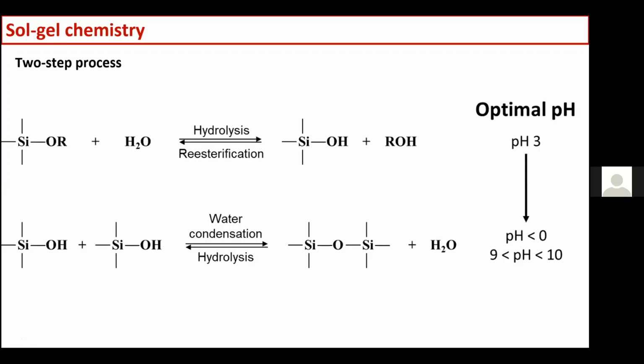And these two steps are optimal at two different pH. So at pH 3, hydrolysis will be favored. And then between pH 9 and 10, we will favor the condensation. Also, it can happen in very acidic conditions below pH 0. And we're going to prepare those mesoporous silica films by playing with these two optimal pH. So I'll show you a bit later.